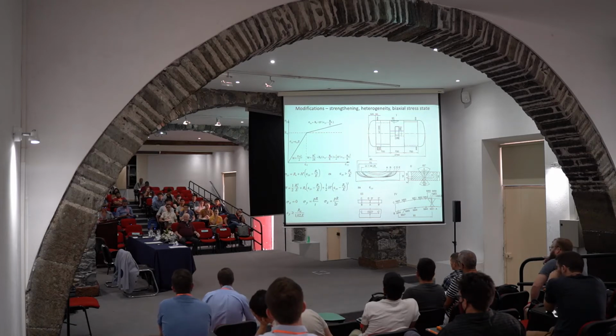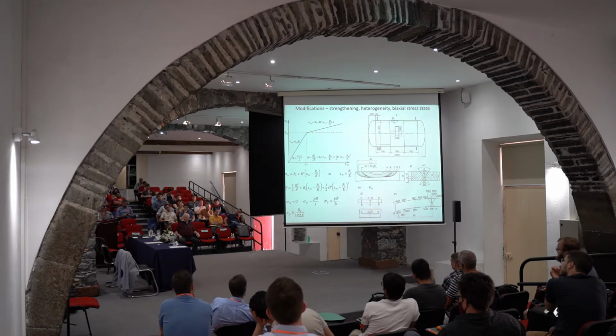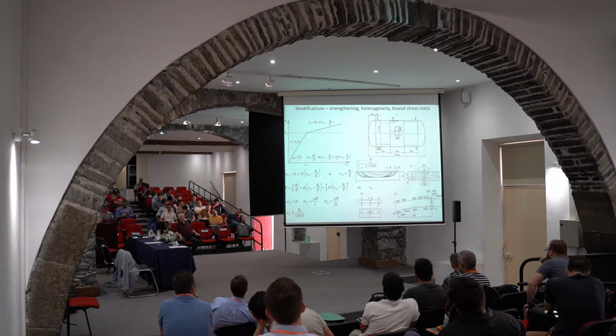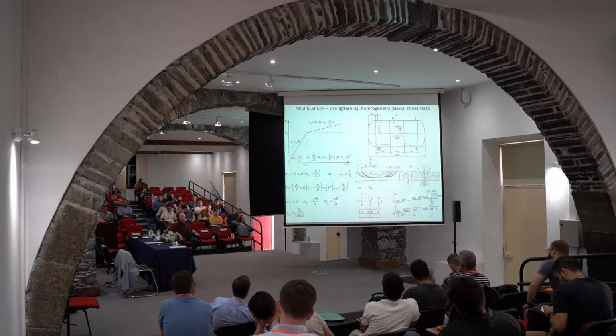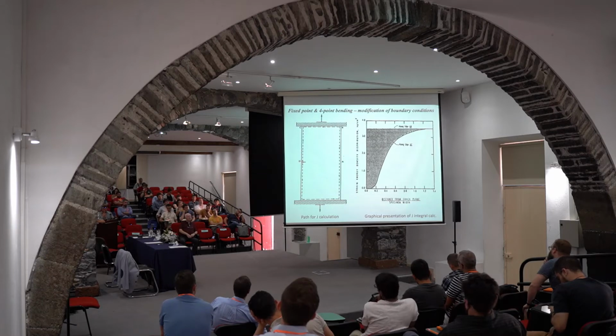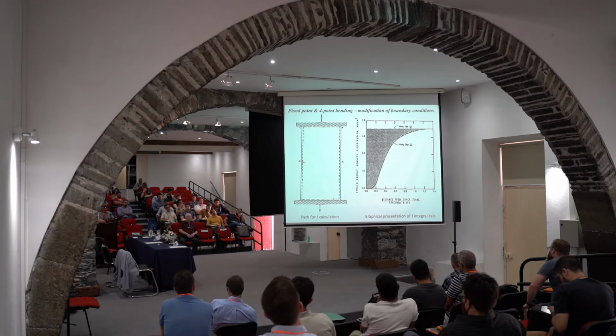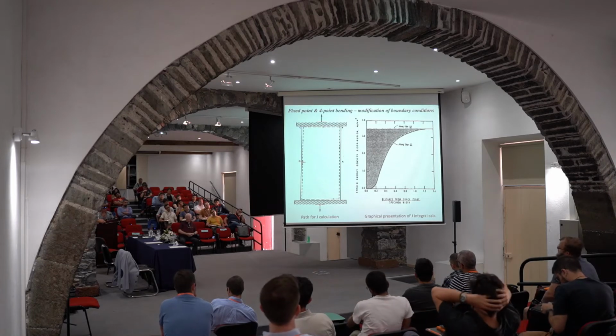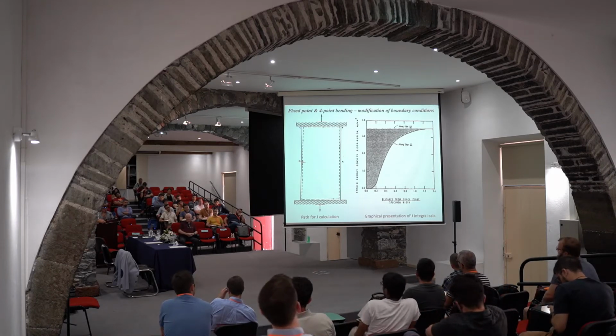So maybe a comment that I missed to say that we made an artificial crack in this cutout piece, and when we put it back, we had the pressure vessel with a crack, and then in a cross section, which is actually shown here on the bottom to the right, we had a bit simplified but relevant case for analysis. Now, as you may have noticed, in this direct measurement technique, we actually reduce J integral to the area between strains measured at the cracked and uncracked side.